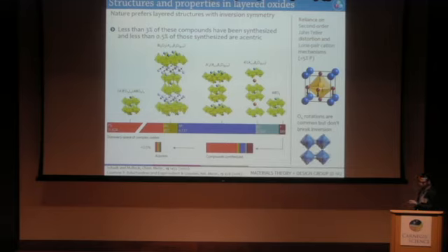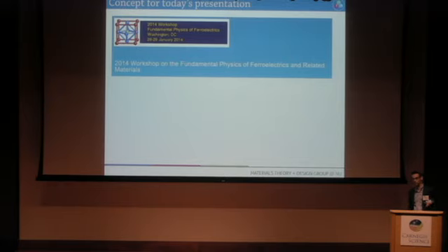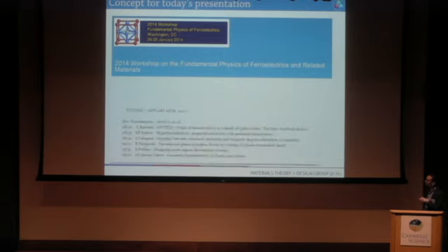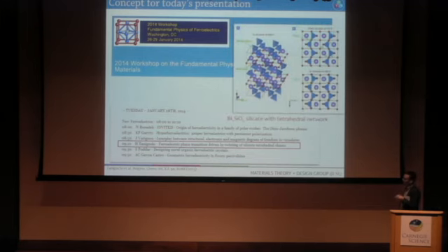So what this talk is really about is how do we circumvent this problem? Okay, and as I mentioned, the idea for this project, or the concepts I'm going to describe today, came from this meeting. It was actually here in this room in 2014. Okay, and there was a presentation by Professor Taniguchi on ferroelectric phase transitions driven by twisting of silicate tetrahedral chains. So he's looking at this bismuth silicate, and I have an SiO4 tetrahedral network which spans the structure. And what he described was experiments which are now published in this journal here prior to the meeting, and electronic structure calculations which really did show that these tetrahedral chains lead to the loss of inversion symmetry in the structure.